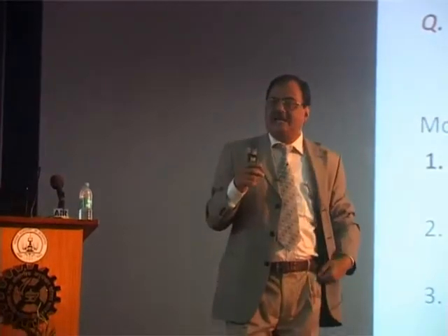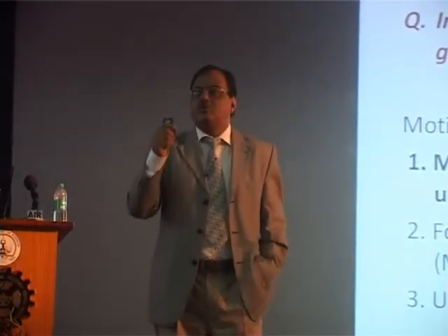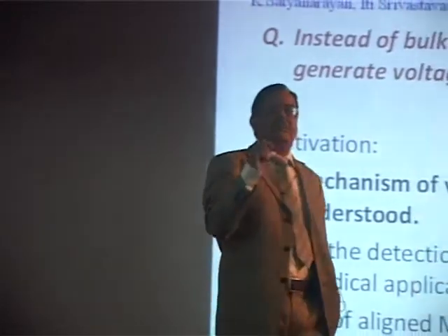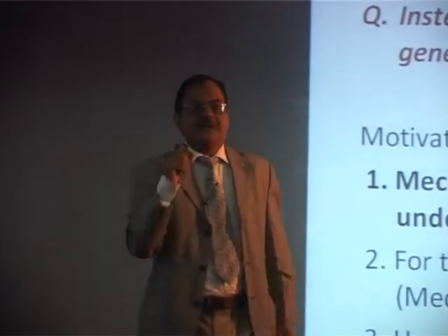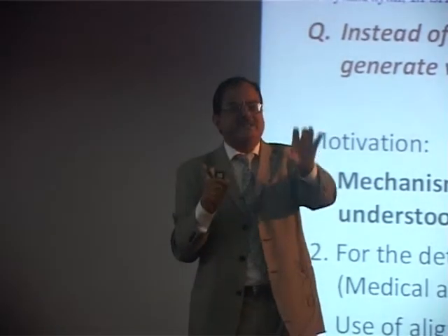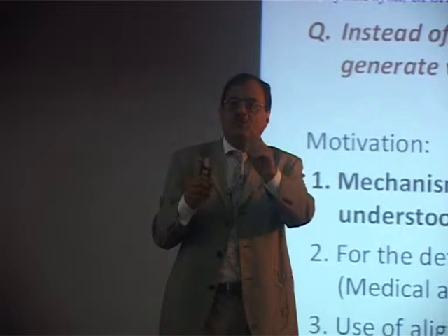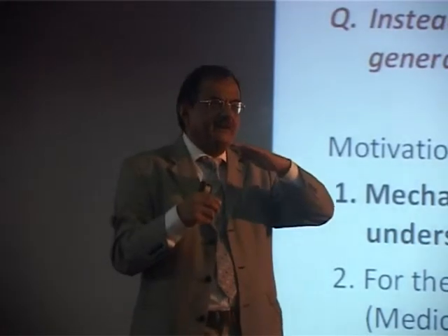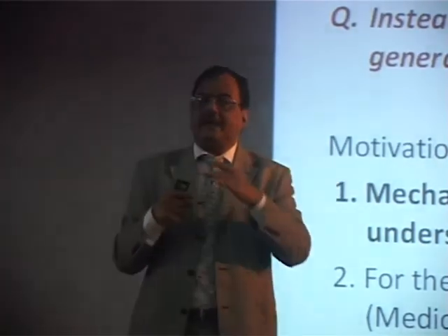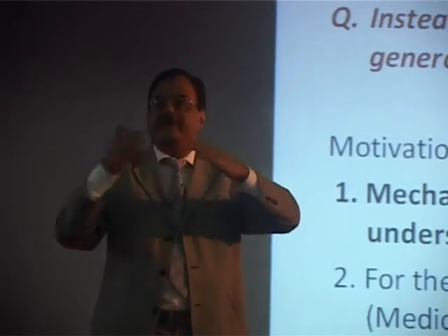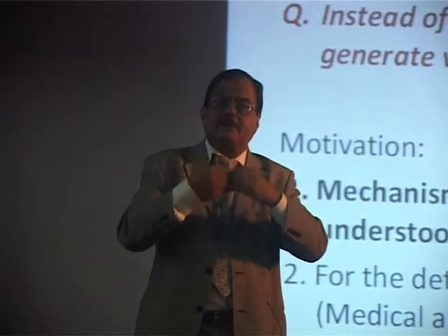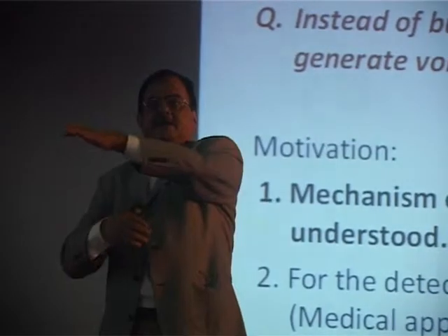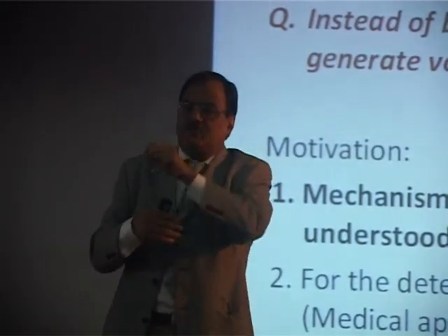So this was a challenge where we did not know that we could use the gas flow effect because it needs much higher speeds. But then my student came out with a very brilliant idea, and that is what we tried out. He said that nanotubes are very sensitive to liquid flow. Very, very low velocity you can detect, even 1 micrometer per second. Can we convert breathing into a liquid flow problem? So the idea was to cool the nanotubes below 5 degrees centigrade, so the water vapors in the breath will condense on the nanotube, and that thin layer of water will be pushed by the breathing, by the gas.